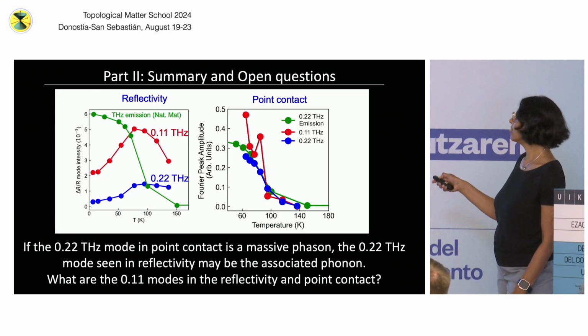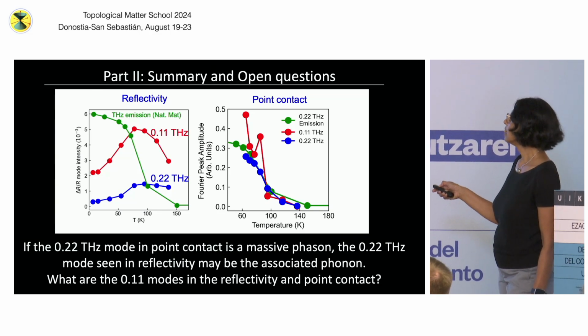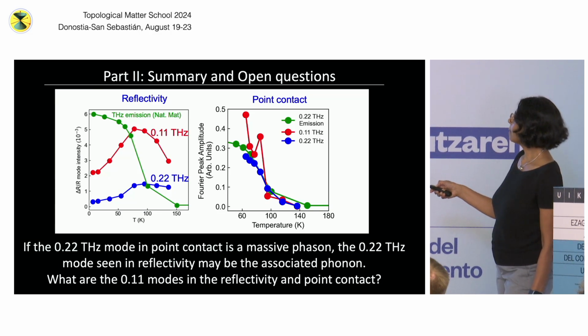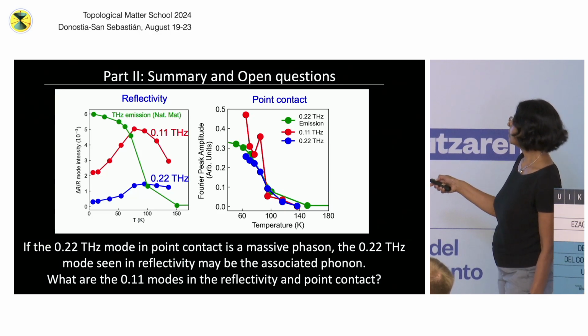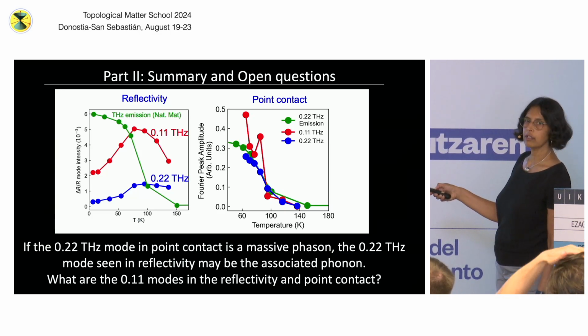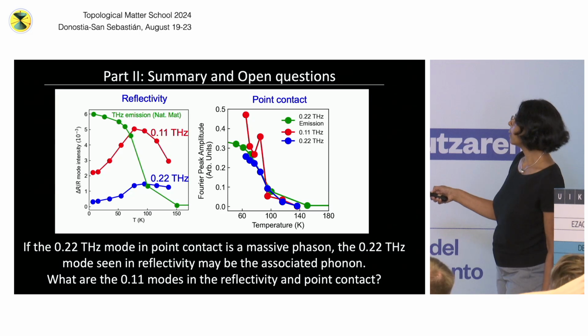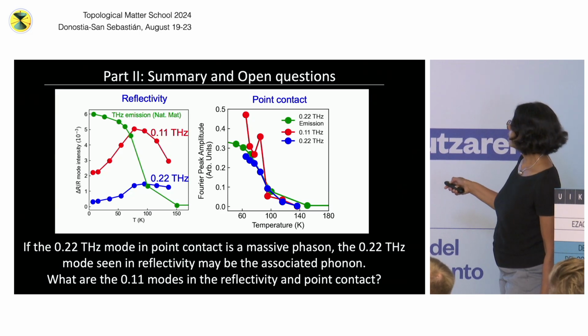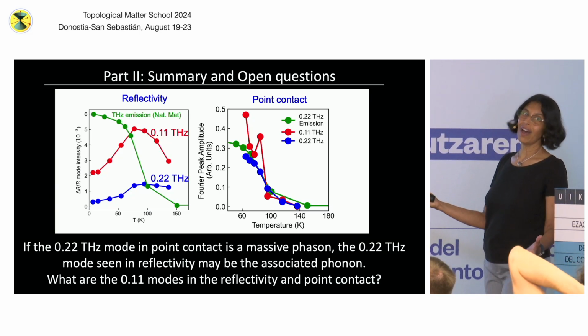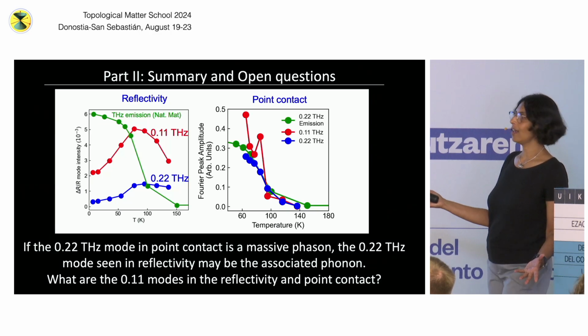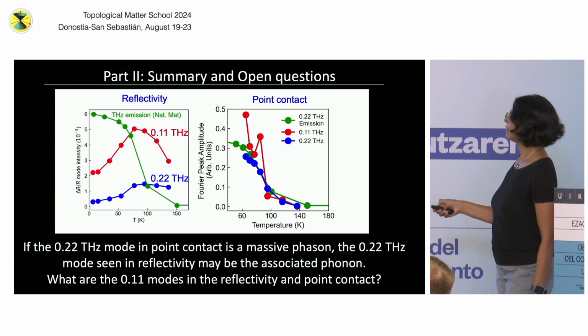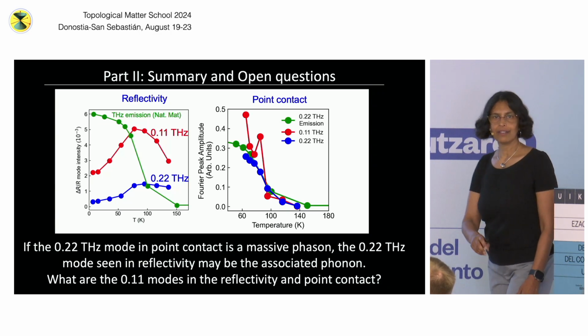We don't actually know how to identify these two modes. Interestingly, there's some sort of competition. This looks like we're measuring phonons, whose intensity is going down, while the intensity of the phason is going up. They're one entity, right? The phonon and the phason. So we don't understand this data. If you have any ideas, let me know. Thank you for your attention.